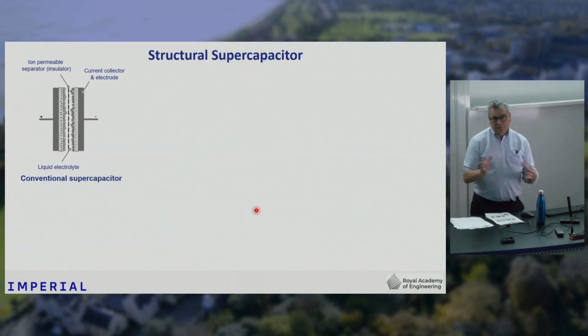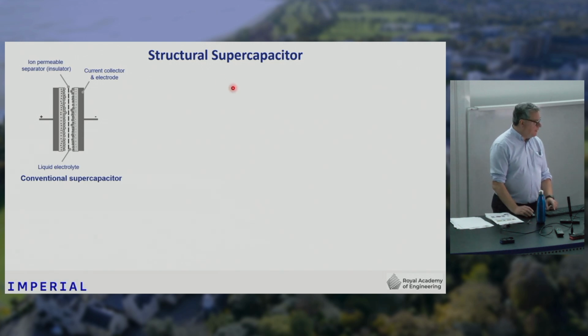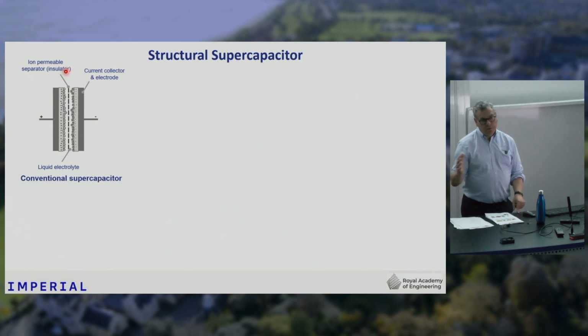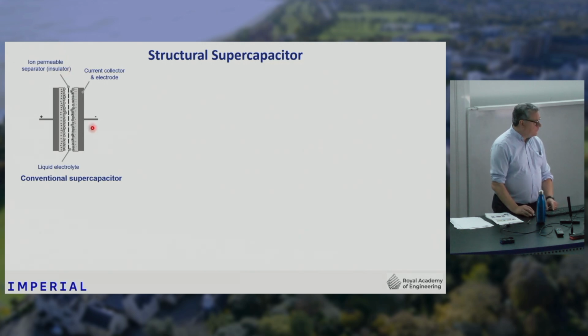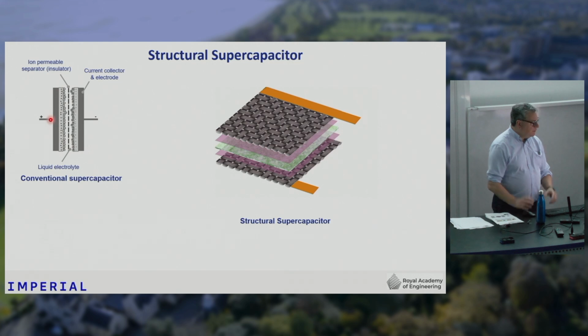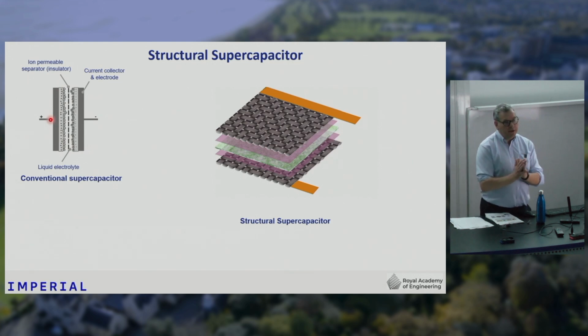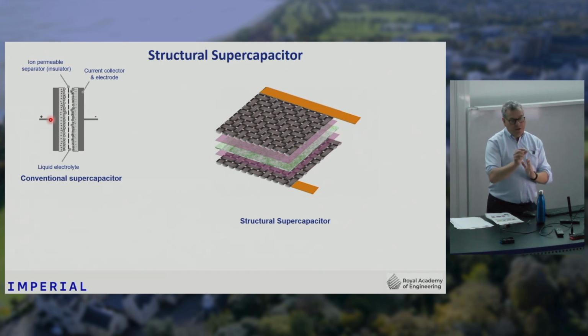So let me explain a bit about how our devices are assembled. Essentially, for a conventional supercapacitor, you have 2 plates which have very high surface area, and those are electrically conductive. Then you have a separator layer which is electrically insulative but allows ions to move through the material. Between those 2 plates you have an electrolyte. That electrolyte consists of a liquid that has ions in it, cations and anions. When you charge the device, you force one set of charges to move to the positive plate, the other set to move to the negative plate, and so it forms what's known as a double layer.